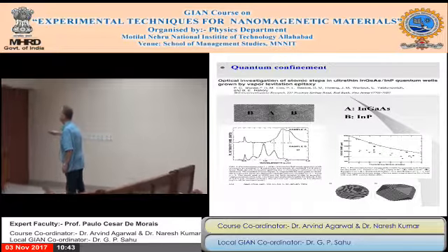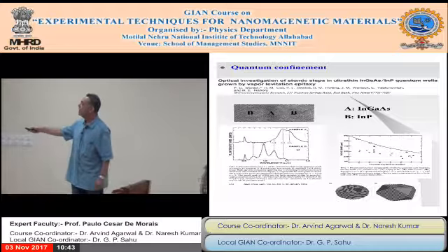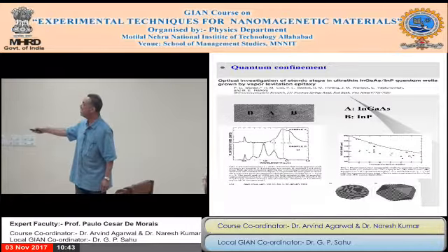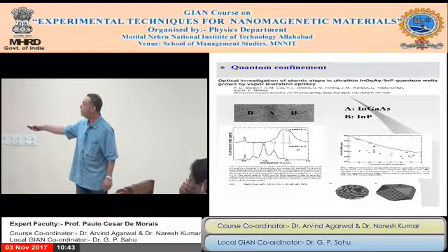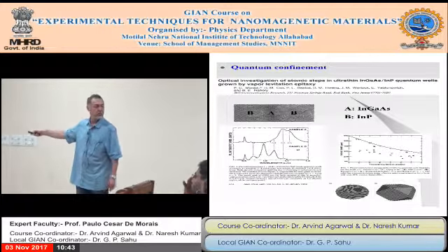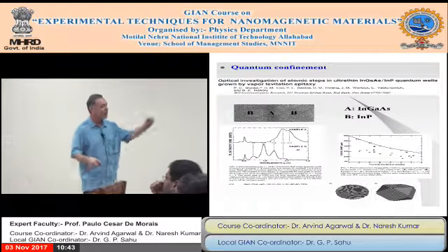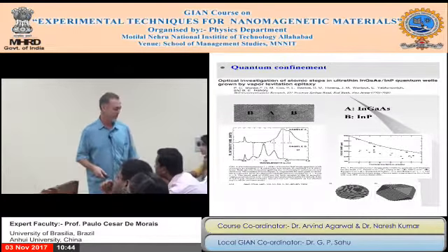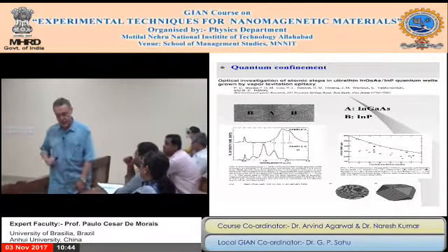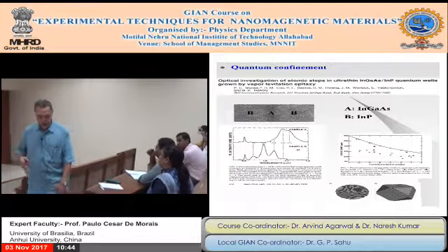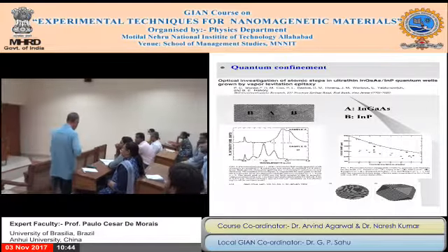Okay. Peak position. So you can see the symbols are experimental data extracted from sample A and sample B. And the solid line is exactly the calculation from the previous equation, Schrödinger equation. I can tell you, the day I took this, and the coming days, 2, 3, 4 days after I got this data,